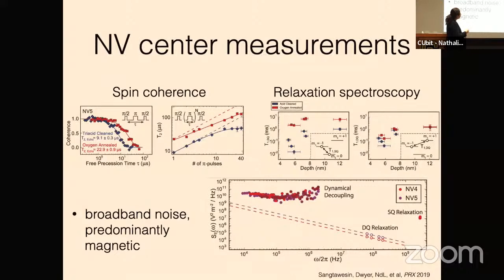We can also do some tricks, like take advantage of the fact that the NV center is a spin 1 defect to do relaxation spectroscopy. In general, these single quantum transitions can be driven by magnetic noise, whereas these double quantum transitions require electric field noise. So the differentials between these tell you something about whether you're looking at magnetic field noise or electric field noise. And then we can make our best attempt at a parameterization where we can plot these in a unified plot. And what we see is that we have a very broadband magnetic noise bath, whereas our electric field noise, if we just extrapolate, is lower than our magnetic field contribution.